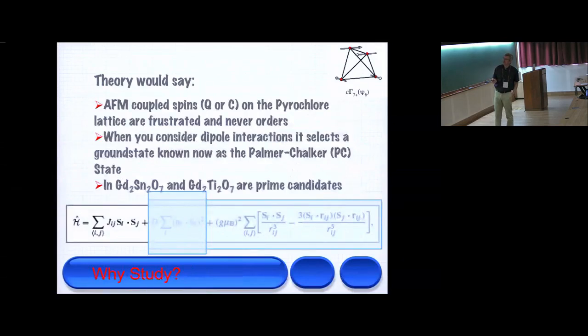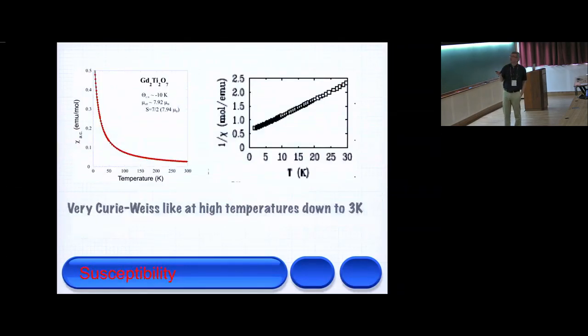If we just have Heisenberg, and then we can add the dipolar, and there should be no gap. Like you saw in the previous talk, all these good, interesting systems at the high temperature limits look like a normal magnet. And many of them will fit Curie-Weiss law, mean field theory wonderfully. And that's a way to get this interaction strength at the paramagnetic limits. It's not always measured properly, but if you get to truly the paramagnetic limit, you'll get this interaction strength, which then if you compare nearest neighbors, you get a measure of J. It's really a measure of all the exchanges, so sometimes the next nearest neighbor is stronger, and that will throw things off, but it's a good measure of the strengths in the system.